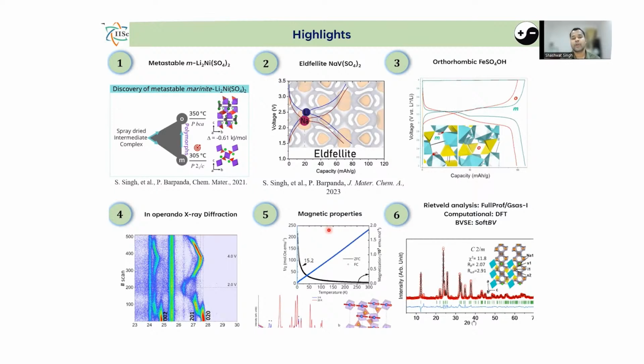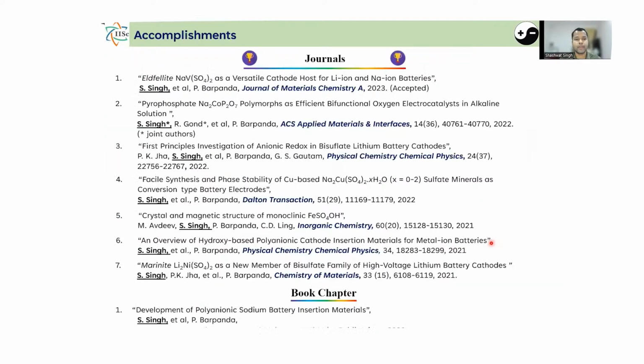And then with the help of a sol-gel route, we have looked at the new compound which acts as a cathode material for lithium and sodium-ion batteries, and there is a possibility of achieving high energy density by applying a two-electron reaction. And then we have unveiled an environment-friendly orthorhombic FeSO4OH as a cathode material for sodium and lithium-ion batteries. Throughout my thesis, I have taken help of in operando X-ray diffraction, and I've also done magnetic analysis and structural solution. And I have also taken help of some of the analysis tools, etc.